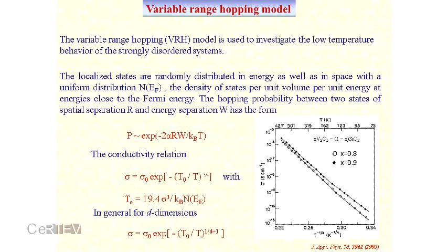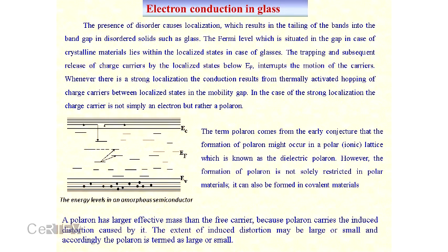As I have told, if the temperature is very low, then we do not have enough phonons to assist the electron to hop from one position to another. In that state, which I have described for a long time, you can see the states here. If we take this atom, this state, as a reference state, then this is the nearest neighbor state, but this is beyond the nearest neighbor state. The energy difference between this state and the nearest state is higher than the energy difference between this state and the one beyond the nearest neighbor. Here the energy difference between these two states is still lower. Under these circumstances, the electron can hop to these states beyond the nearest neighbors.